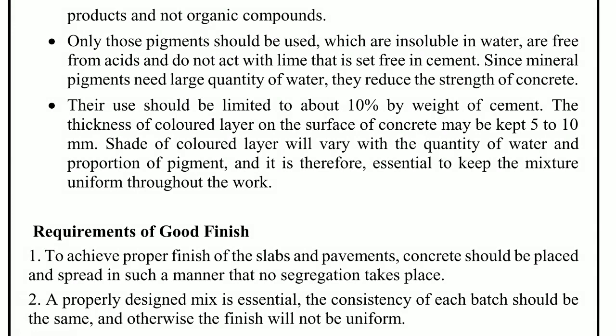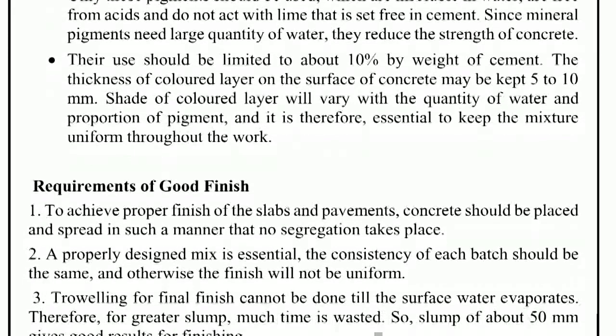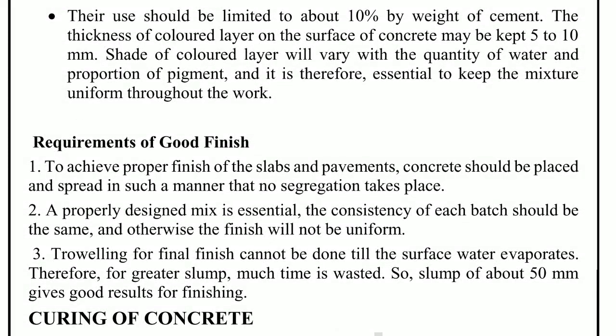Pigments should be free from acids and should not react with the lime set free in cement. Since mineral pigments need large quantities of water, they reduce the strength of concrete, so they should be limited to about 10% by weight of cement. The thickness of the colored layer on the surface of concrete may be kept at 5 to 10 millimeters.